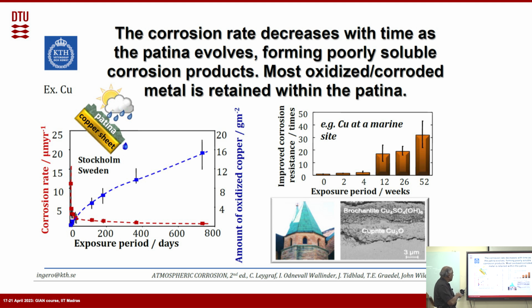And this is also what it says, that is improved corrosion resistance over time. Over the weeks, this copper dissolution rate is reduced because you have an increase in this patina formation and things like that. So that is naturally what you see in the case of copper, because patina is forming, and that way this dissolution rate is decreased.